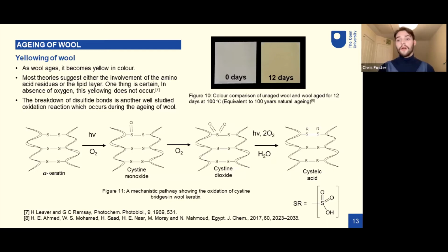So we know that wool becomes yellow with aging, but there's been lots of different reactions suggested to be responsible for this yellowing colour. Some theories suggest an involvement of the amino acid residues, so that's the side chains in the amino acids, and others suggest the destruction of the lipid layer. One thing that we do know is that oxygen is involved in the process. It's an oxidation process of some sort. And this can be seen because if you carry out aging in the absence of oxygen, this yellowing doesn't occur.